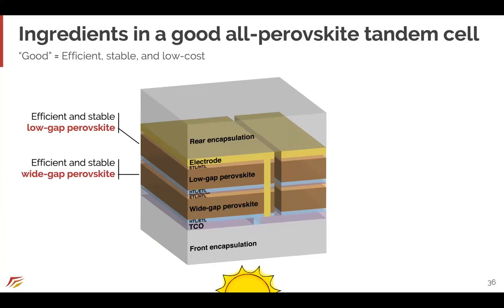You also need to make a stable and efficient wide gap perovskite, which introduces bromine, which can cause phase segregation and other stability challenges as well. You need a rear electrode that actually physically blocks ions from reaching the metal contact or simply doesn't react with ions in the perovskite and other layers. And these problems usually show up over longer times, so we need to be aware of these.